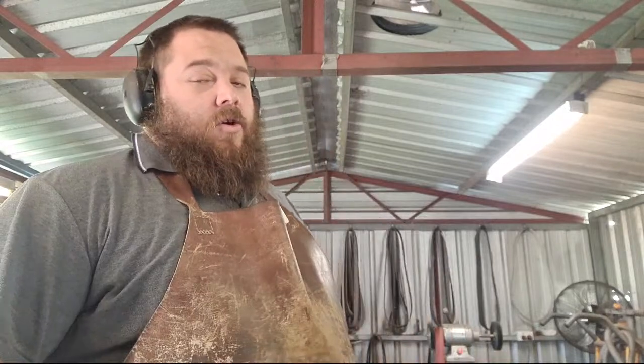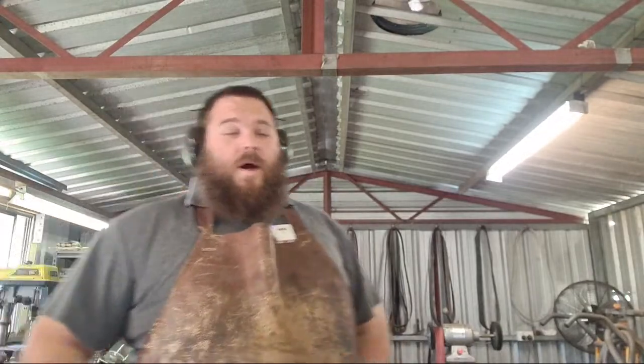So yeah, it's really important that you manage to get that force all the way through the billet in order to get really good welds. Kyle Royer, when he was doing his keynote speech at Blade Symposium, said basically that you're looking for about a quarter inch of movement, quarter to a half inch of movement in the billet in your welding phase. Now, of course, the bigger your billet, the more force is required. But the bigger your billet, the longer it will hold welding temperature.